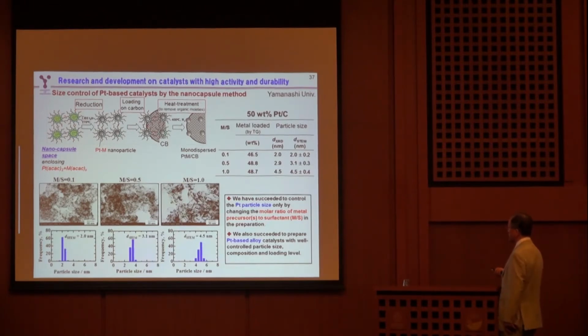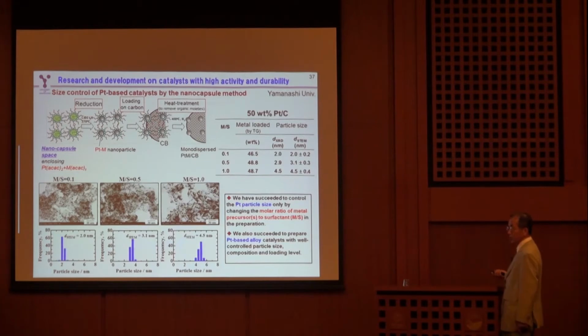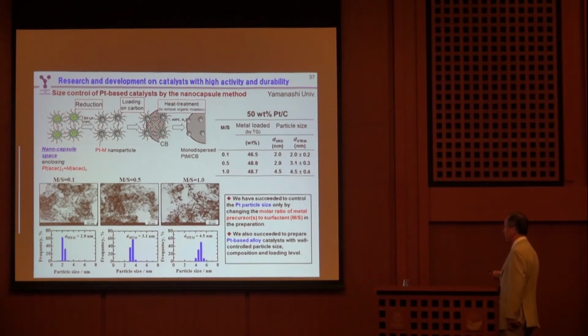We have succeeded in controlling the particle size only by changing the molar ratio of metal precursor to surfactant in the preparation. As you can see, by changing the ratio, we can get different particle sizes with very narrow size distributions. And also, we succeeded in preparing the platinum-based alloy catalyst with well-controlled particle size, composition and loading level, as shown next.